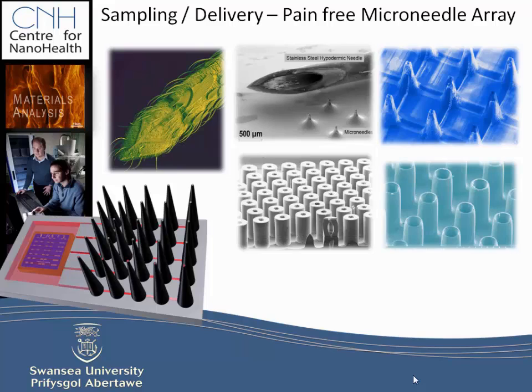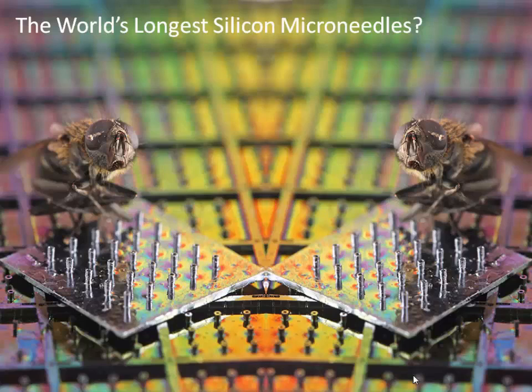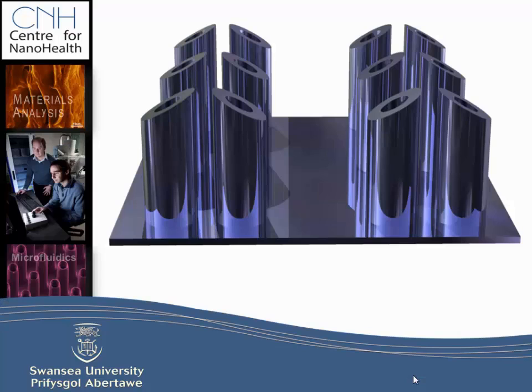Okay. So that's what we're doing, trying to make these microneedles. There, in comparison, is a hypodermic needle, so you can see which one you probably rather have injected into you. So different microneedles are polymer. These ones are polymer. These ones are silicon. What you see, these needles are not actually sharp yet. So the tip is not sharp enough. That won't actually penetrate into the skin very effectively unless you push really hard. So the new design is a beveled needle or sharp needle tip.